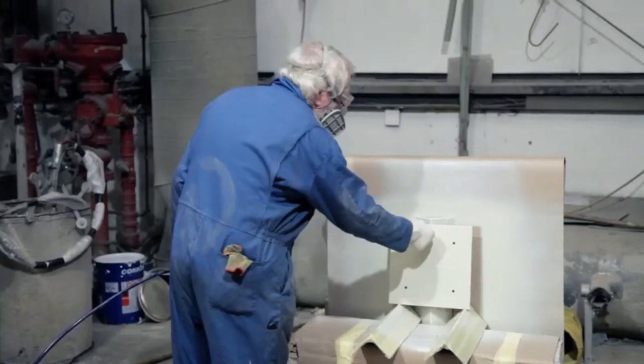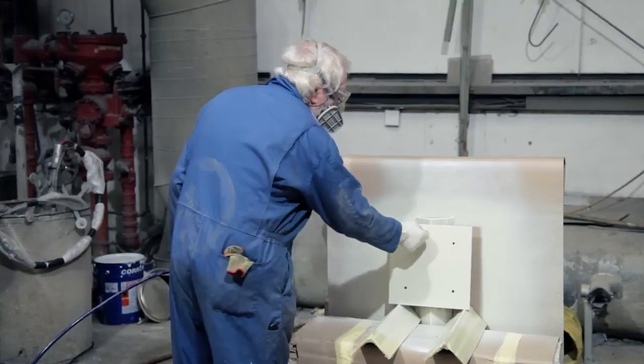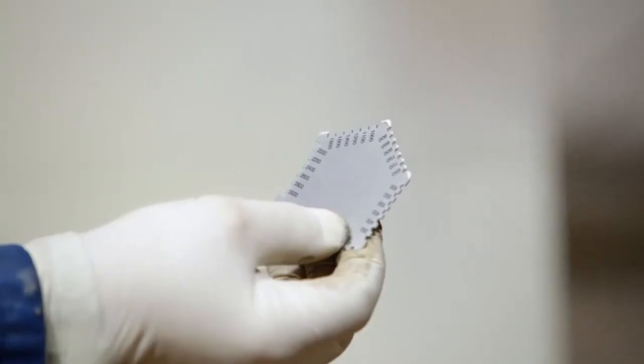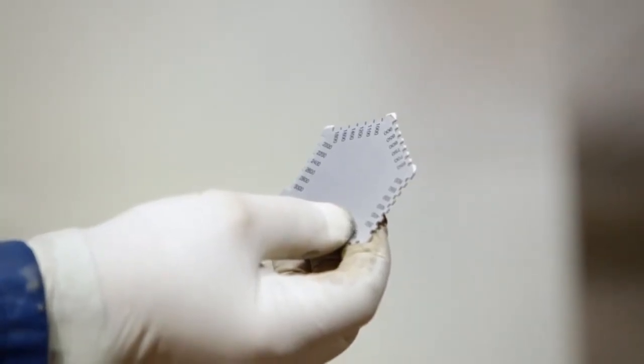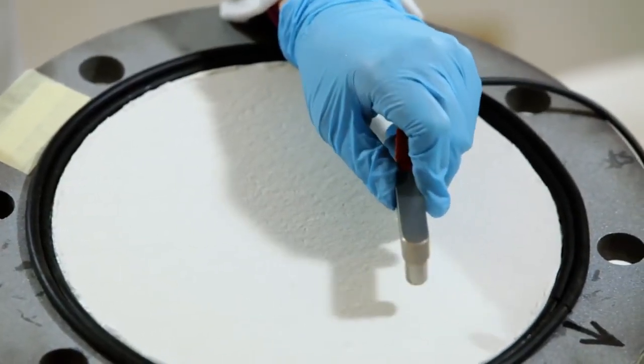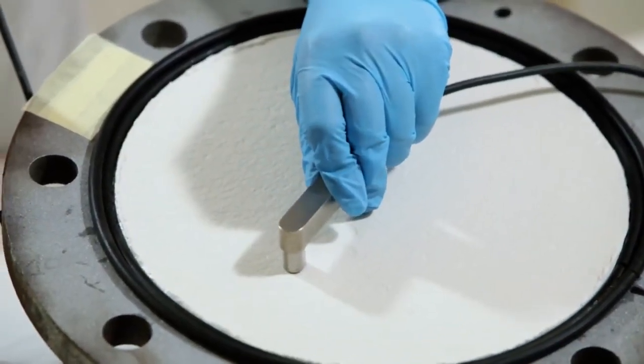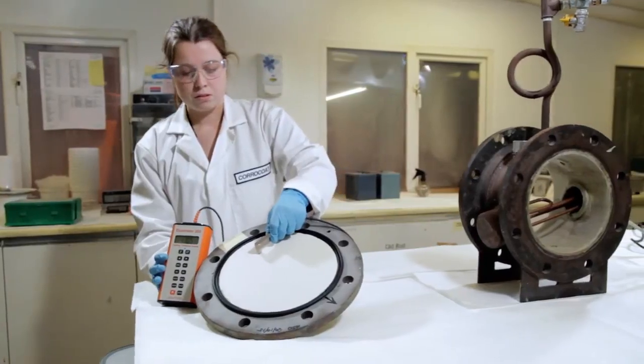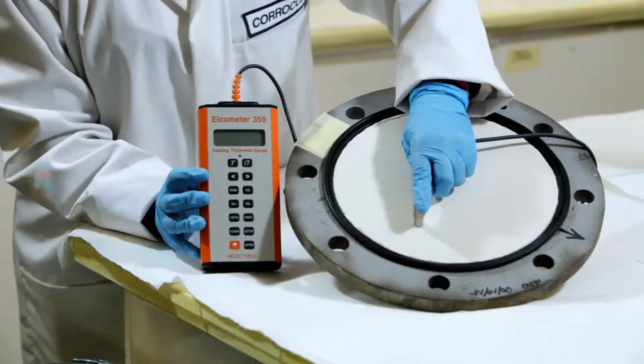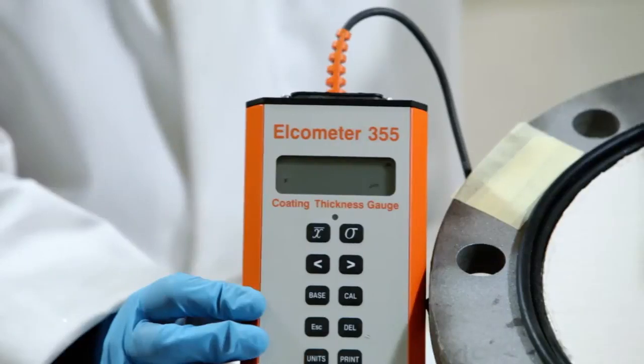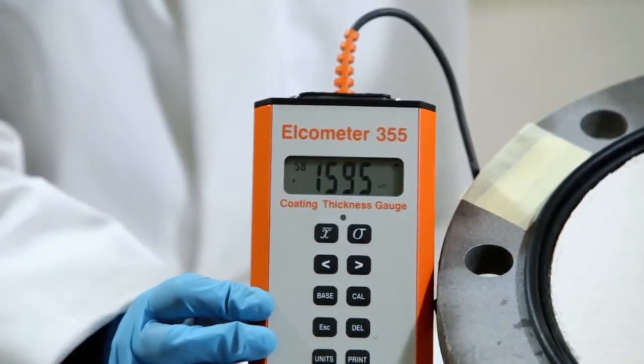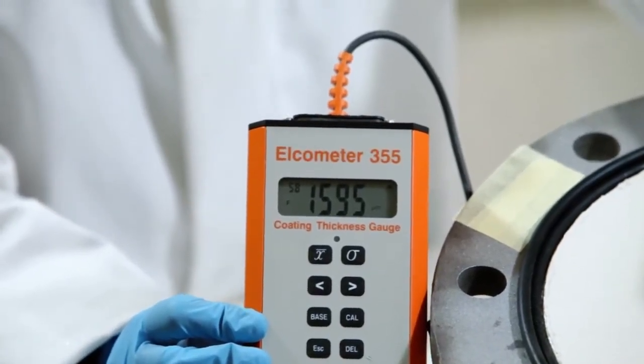Wet film thickness of the coating is checked in an area of the panel not subjected to the media and outside of the gasket sealing area. Subsequent dry film readings are taken and both wet and dry readings are recorded. The dry coating thickness must be within 10% of the nominal DFT, or where a minimum is specified, the maximum reading shall be no more than 10% above the minimum.